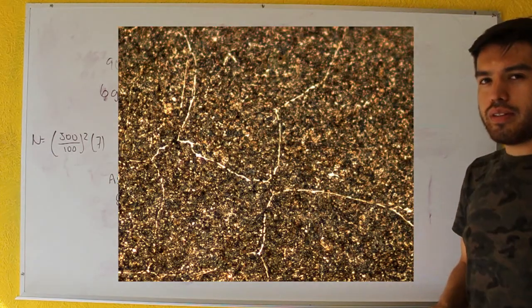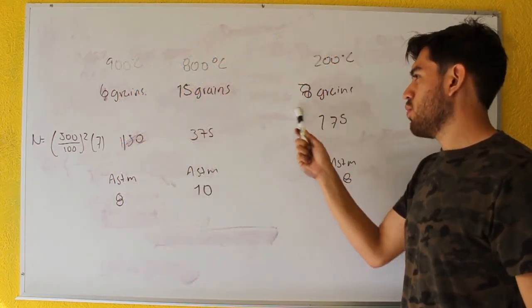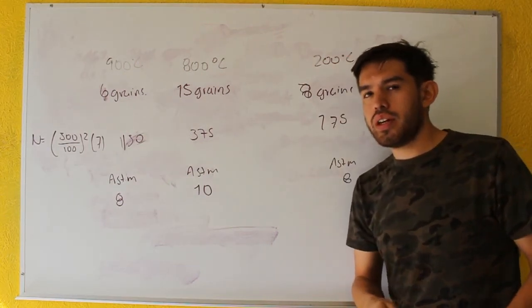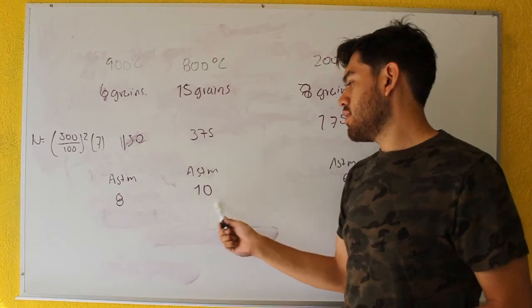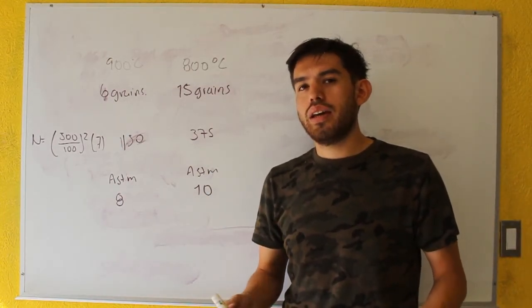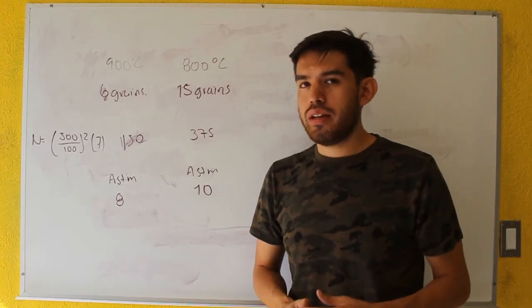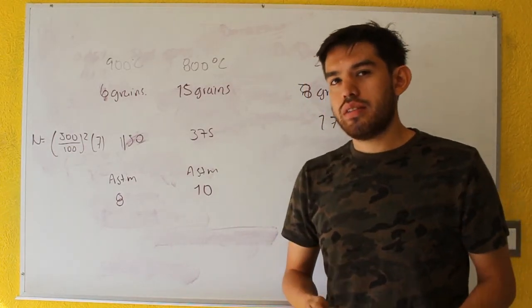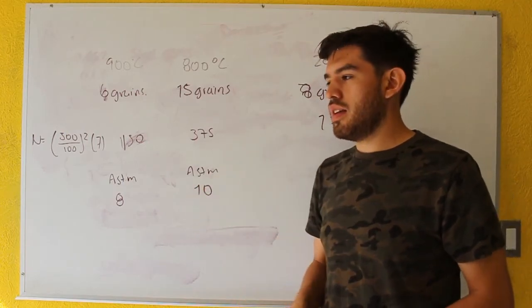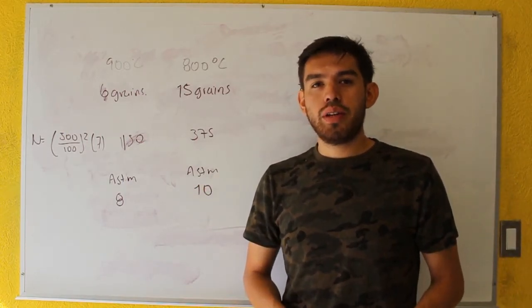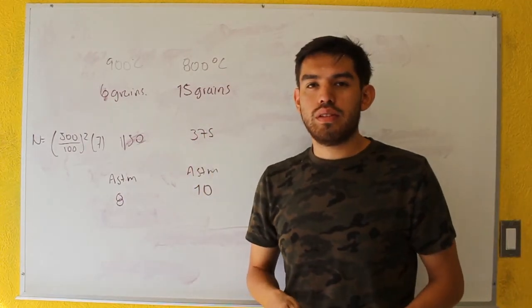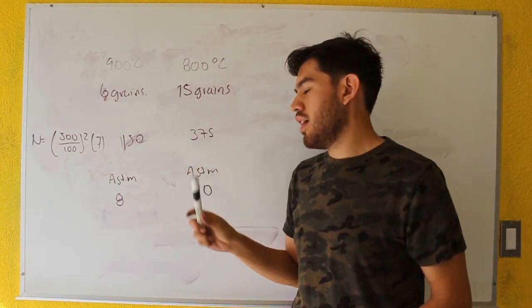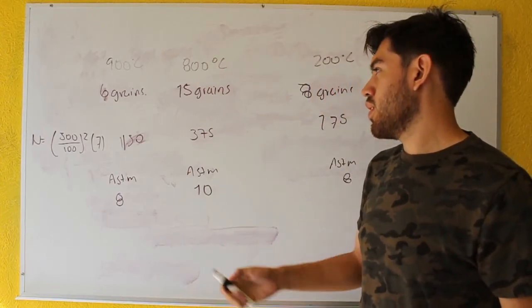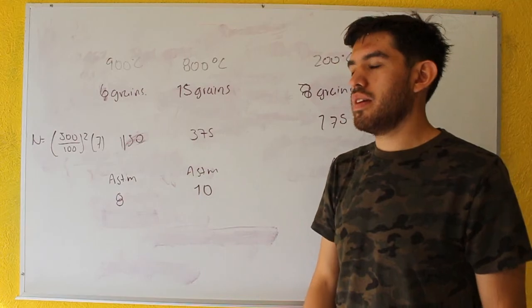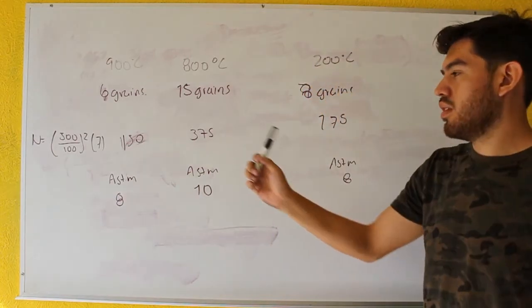Finally, the third piece, on which we did 3 treatments, and we obtain 8 grains and an ASTM of 8. We want to remember that if the ASTM number is bigger, we get better properties. We can see it in the second piece, because we obtain this 10 in ASTM number, and in this piece we got higher results in the hardness test. So we can conclude that this one has better properties, and this one has the worst properties of the 3 pieces.